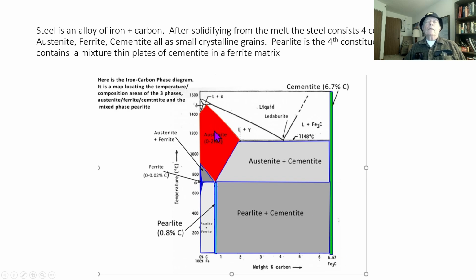Now, the austenite region is red, and you can see that it will dissolve quite a bit of carbon. Go down here, 2%. The ferrite region occurs at lower temperatures, and it is basically pure iron. It could only contain 0.02%, which is shown as an exaggeration here. The other four regions are mixtures, they're labeled clearly so you can see what they are.